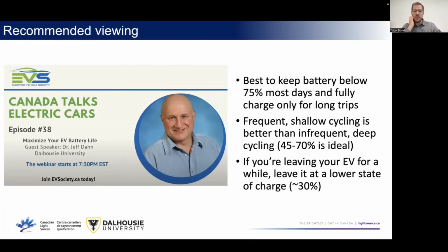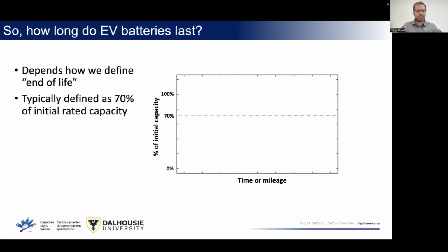If you're leaving your EV for a while, like for weeks or months, it's best to leave it at a lower state of charge to keep that voltage down, say something like 30%. But if you need to charge it up to 100% for long trips, by all means do it. If you want to get that extra service lifetime out of your battery, these are the main ways to do it. But I'd suggest you check out Jeff's webinar, because he'll explain the reasons behind all of this in exquisite detail, and I won't cover all of it today.